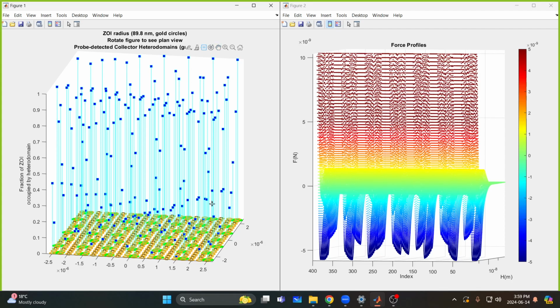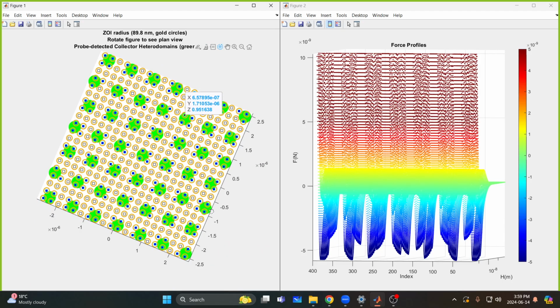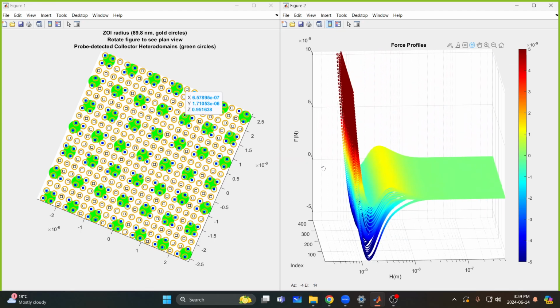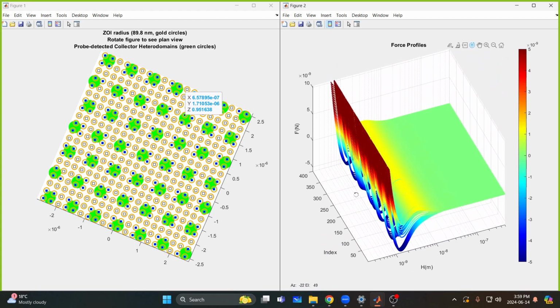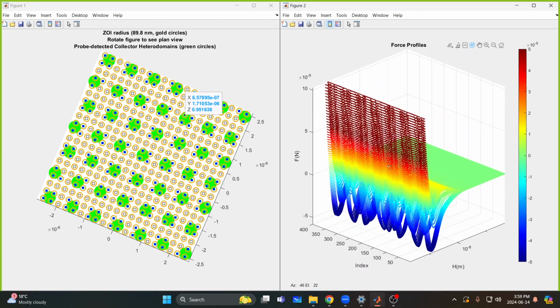But what's really interesting about this is that we know that colloids are stochastic. Not all of them attach, not all of them detach in response to perturbations. And a critical function that nanoscale heterogeneity provides that no other DLVO aspect provides is a stochastic outcome. Whether the colloid trajectory overlaps the heterodomain sufficiently to allow attachment is a stochastic process. And so this is the only element I know of that creates the stochastic impact.